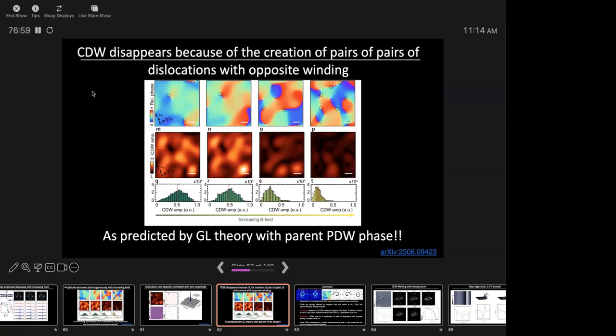We can't see the vortices in this compound clearly, but we can take all these dislocations and put them on top of each other. This is just for one of the 3 solutions. We can add all of them together and ask if there's some bunching, and actually there is some bunching, and the number of bunches corresponds approximately with the number of vortices you expect. But I have to say our field of view is not big enough to do anything statistically significant.